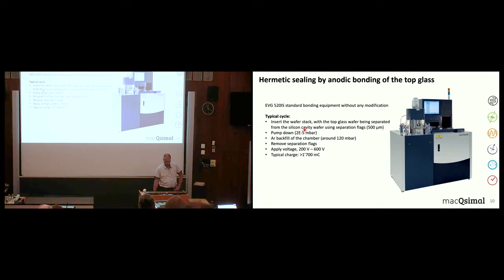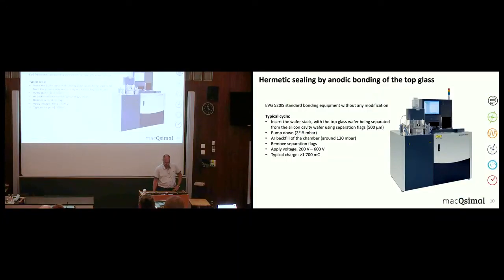So here we insert the wafer stack with the preform down and the top glass on top, and the two are separated from each other with separation flags of about 500 micrometer thickness. So this allows us, when we pump down the chamber to 2 times 10^-5 millibar, to also have the same vacuum inside the cavities before being brought together in close contact.